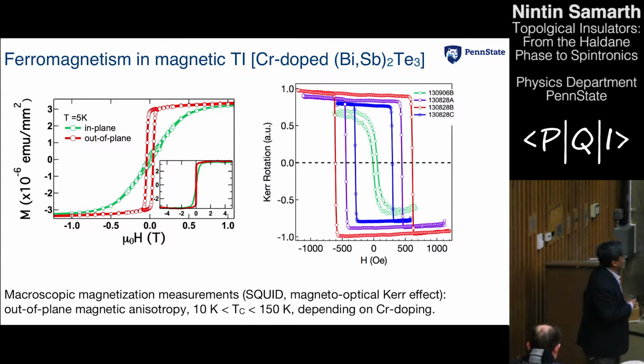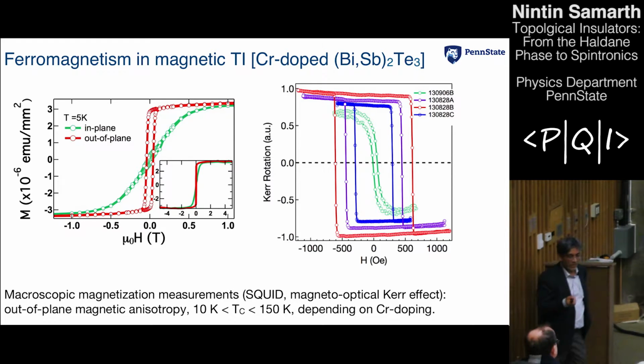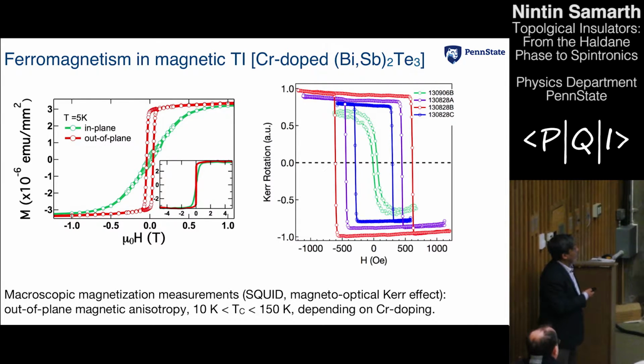That means that if you sweep a magnetic field to some high value, bring it back to 0, and then reverse the field, if you're measuring some property that is characteristic of the alignment of the spins, then you should see a hysteresis loop. And that's indeed what we see. You see the hysteresis loop in a SQUID magnetometry measurement when the magnetization is pointing out of plane. If you put the magnetic field in plane, then the hysteresis loop goes away. That tells you that the magnetic moments are pointing out of plane.